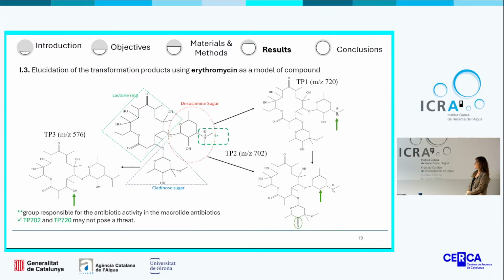The elucidation of the transformation products using erythromycin as a model compound was also performed. According to this result, 3 different transformation products were identified. The first one corresponds to the demethylation of the amino group in the desosamine sugar. The second one was a result of the elimination of a hydroxyl radical in the desosamine sugar, and also the oxidation to a ketone group in the cladinose sugar. And the third one was a consequence of the cleavage of the cladinose sugar. From all these identified transformation products, just one of them still preserves the group responsible for the antibiotic activity, and therefore is still a threat.